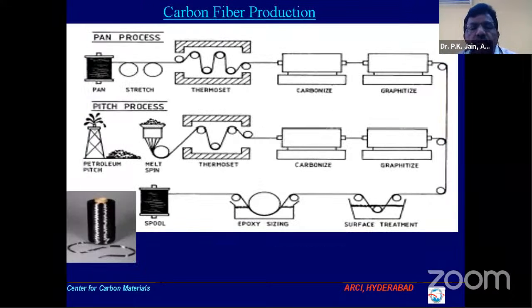Now, processing of carbon fiber looks to be simple but is a little complicated, and that's the reason in India not many, one or two companies are trying, but still a long way to go. You take an acrylic fiber, PAN, you stretch it under special conditions, and the thermoplastic will become a thermoset, and now the polymer is a stabilized polymer, and then the fiber is carbonized. Carbonization means a heat treatment of 1,000 degrees and plus, and then you graphitize it. Graphitization means about 2,500 degrees and above.